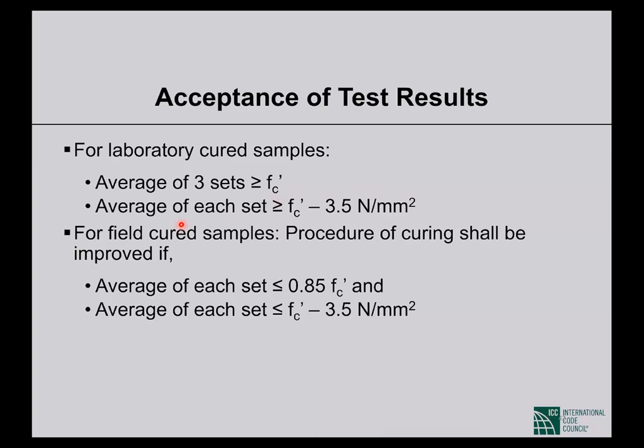But the average of 1 set may be less than fc prime, but not less than 3.5 megapascal below it. So suppose your design strength is 21 megapascal, say. Now you are getting an average of 1 set of 18 megapascal, right? So is that okay or not? That is okay, no problem, because that is within this limit. But the average of 3 sets must be greater than fc prime. Okay, this should be clearly understood.